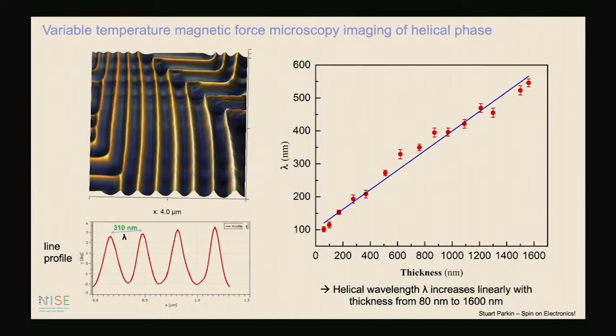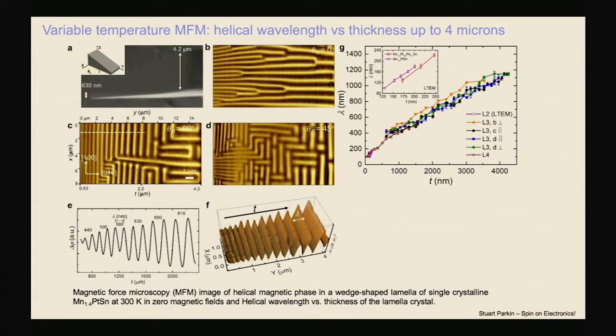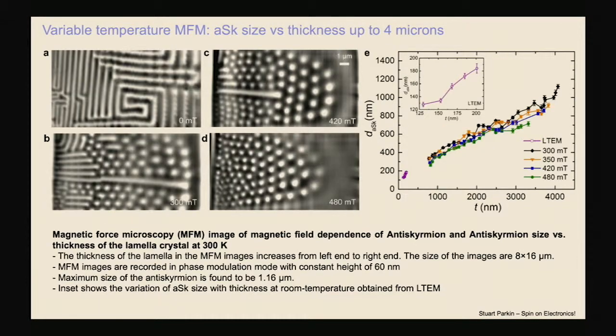The period increases linearly with thickness, it seems, and now we can go to even thicker, up to 4 microns, and we still see a continuous variation of both the period of the helical phase and the size of the skyrmion, ranging from here 100 nanometers up to more than a micron. And that means that we can actually observe these objects using Kerr microscopy.